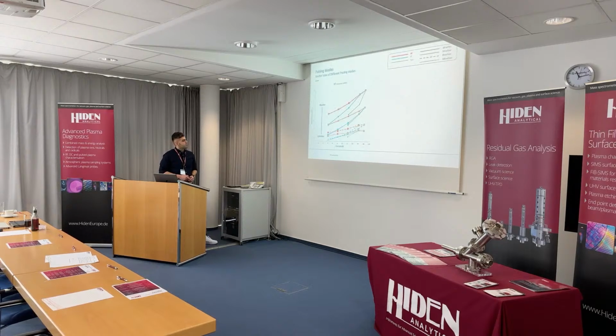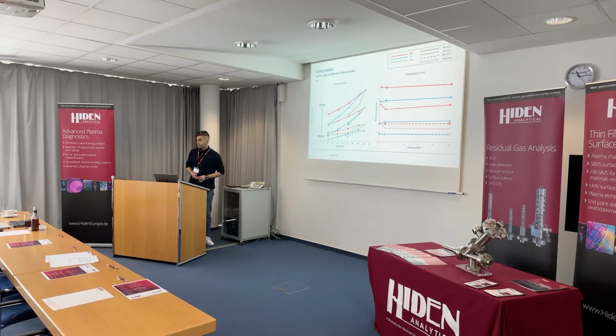And this is the duty cycle effect on sputter rate. When the duty cycle increases, the sputter rate increases for different pressures, for HF pulse, LF pulse, and sync pulse. And this is the frequency effect on sputter rate. So you see also the frequency doesn't have so much effect on sputtering.